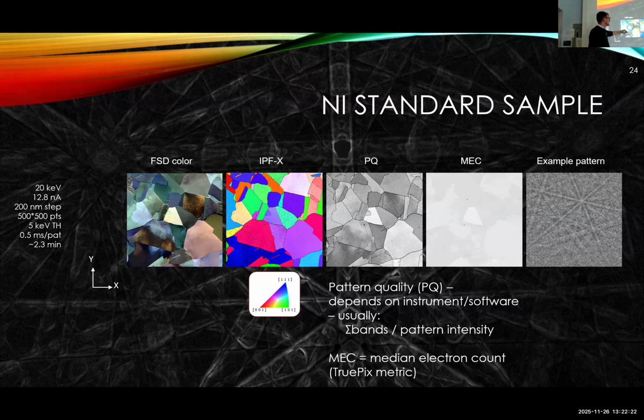And then I've indexed each of the diffraction patterns, and I can get the crystal orientation. And for every pattern, I can tell you how sharp the pattern is. So that's the pattern quality. It's like a Fourier transform power spectrum type number. And then in this case, when I use a direct electron detector, a new advance we have at UBC, we can also measure the median electron count. So we can count the number of electrons hitting our detector. And this is our diffraction pattern that was used for this experiment in here.